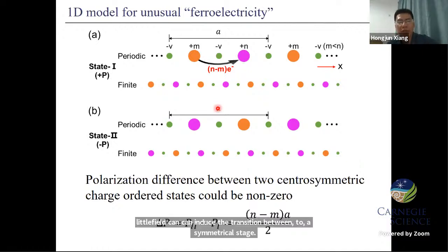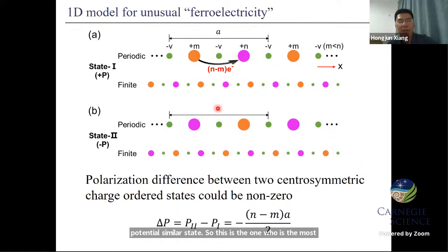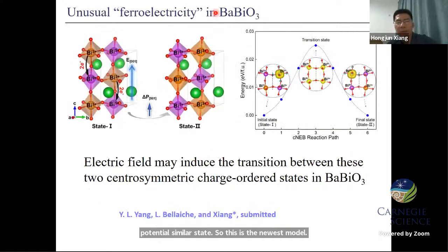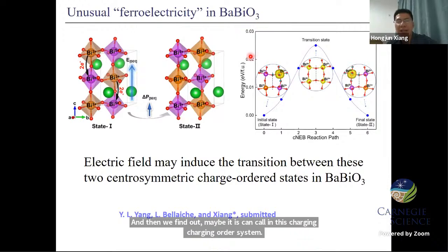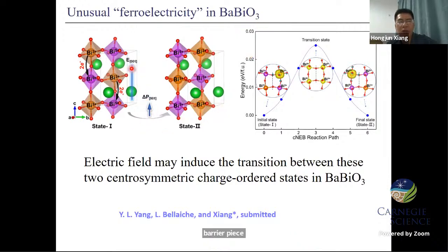So this is the one-dimensional model, and then we found that maybe this could occur in this charge order system, barium bismuth oxide. We suggest if you apply an electric field along this direction, then the charge transfer will occur for both chains, and this is the transition state of this transition. So this is basically what we proposed in our recent work.